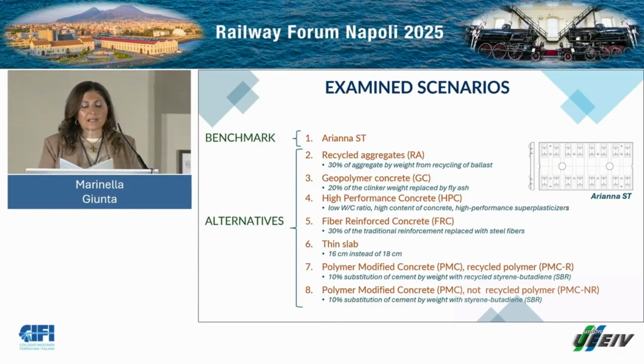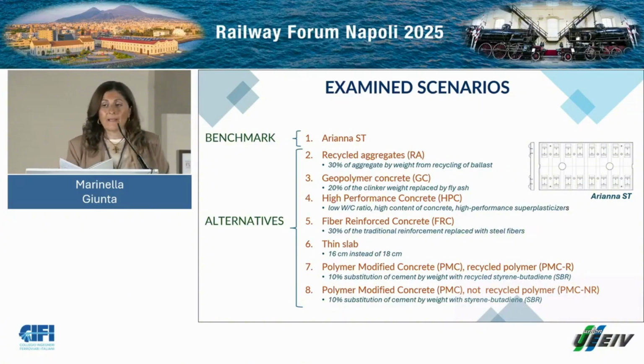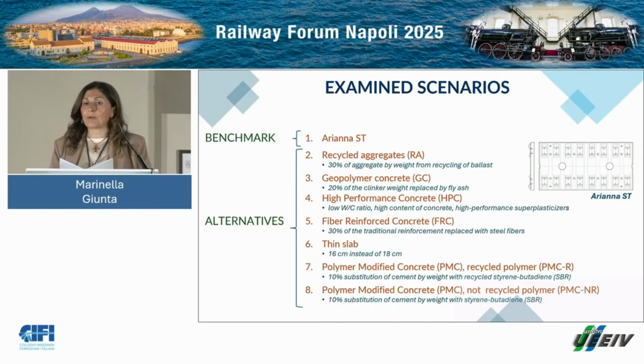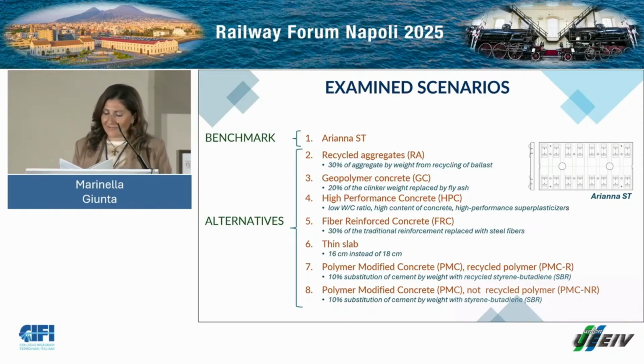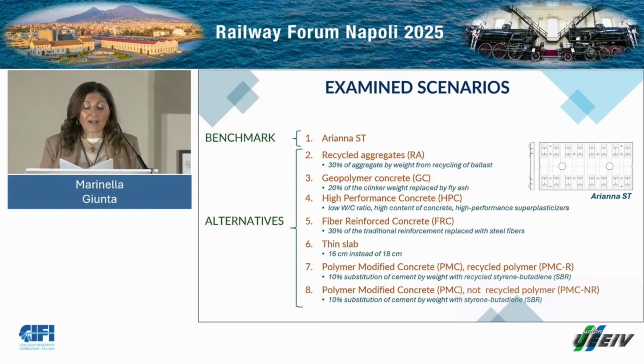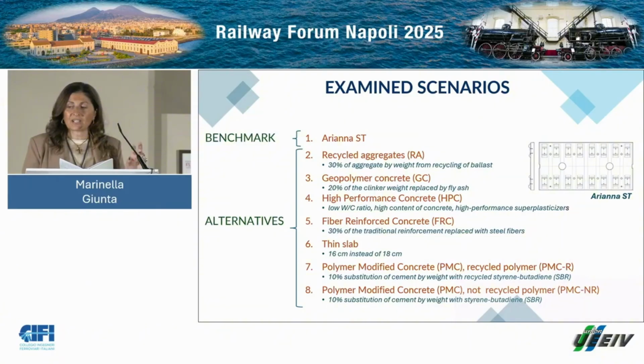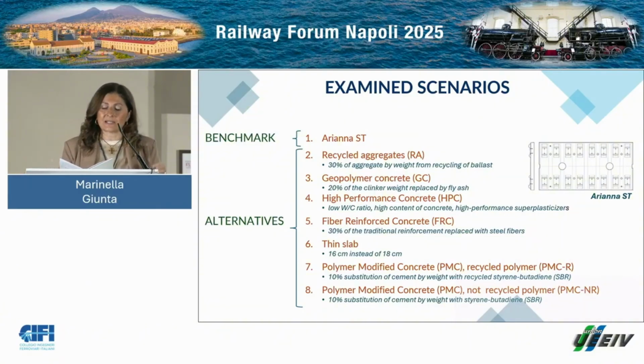For instance, we considered a scenario in which 30% of aggregate by weight is from recycling, in particular from recycling of dismantled ballast. Another scenario considered the use of geopolymer concrete, in which 20% of the clinker is replaced by fly ash. The use of high-performance concrete characterized by low water-cement ratio, high content of cement, and high-performance superplasticizers. The fiber-reinforced concrete, in which 30% of traditional steel reinforcement is replaced with steel fibers.